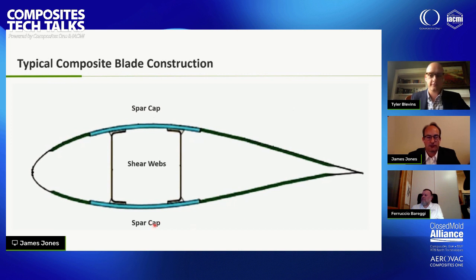The shape is fairly simple, but there are distinct laminate zones in the blade shell. This blue area at the top is pretty solid unidirectional laminate because it bears most of the flap-wise bending stresses. That might be made from unidirectional fiberglass or carbon fiber. Out on the aerodynamic portion of the blade shells, we don't need much strength. We need to resist buckling and have some stiffness, so we have fairly light laminates that are stiffened with core materials, be it balsa wood or PVC or PET foam.